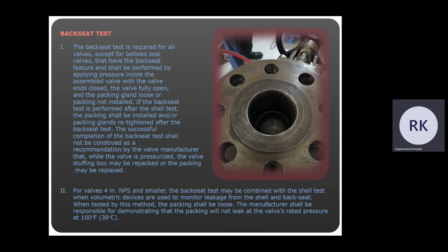What about the backseat test? Because we have been talking about backseat test. Backseat test is required for all valves except for bellows seal valves that have the backseat feature, and shall be performed by applying pressure inside the assembled valve with valve ends closed, the valve fully open, and the packing gland loose or the packing glands not installed. So if the backseat test is performed after the shell test, then the packing shall be installed and the packing glands retightened after the backseat test. Successful completion of this backseat test shall not be construed as a recommendation by the valve manufacturer that while the valve is pressurized, the valve stuffing box may be repacked or the packing may be replaced.